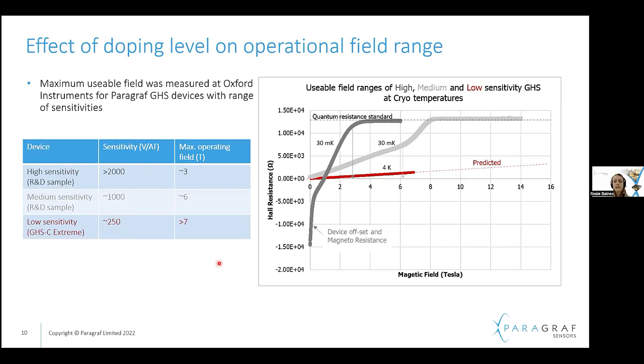These 3 devices were tested over a wide field range. You can see that with the high sensitivity, we see a high response, and at about 3 Tesla we're reaching the first of those quantum resistance plateaus that I showed earlier. Whereas by controlling the carrier concentration, we can have a range of different responses. By bringing it down to the level of this red one at the bottom here, we can see that the response carries on in a linear fashion. We predicted that it would carry on, as it's quite far from this standard.